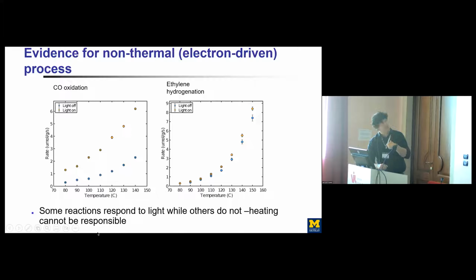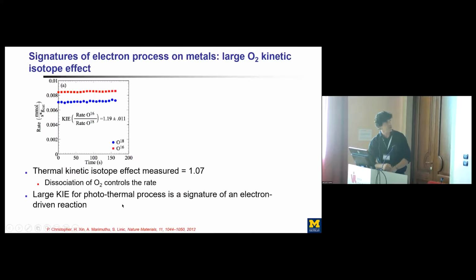And what we see here is that you actually do not see enhancement in the reaction rate. If you saw heating of the entire system, you would expect that this rate would go up as well under the influence of the thermal flux. However, under the light influence, the rate does not change. As you heat the sample, the rate goes up, but as you shine light of this intensity on an identical catalyst, you do not see the rate going up. So this was kind of an indication that we might have something that has to do with these energetic electrons interacting with the adsorbates or with oxygen.